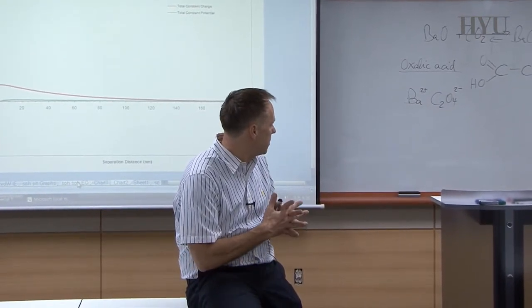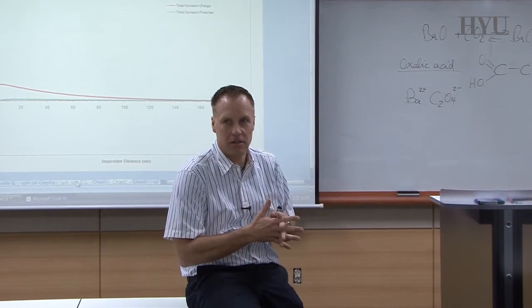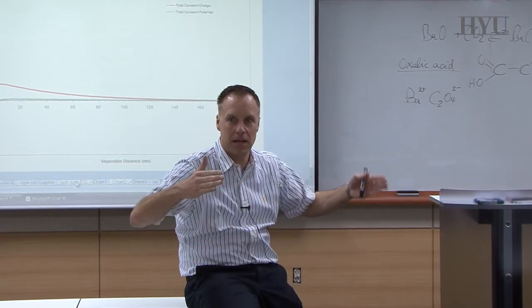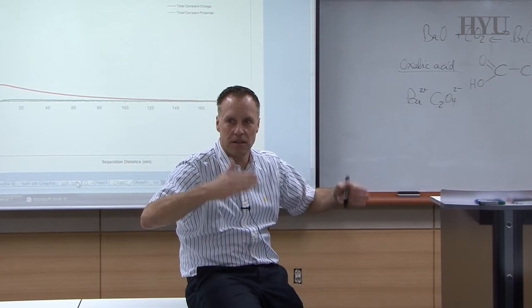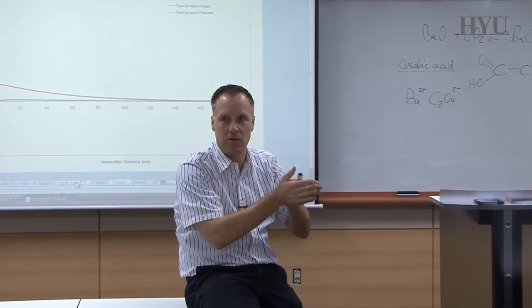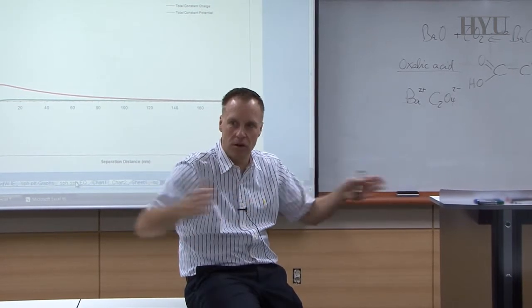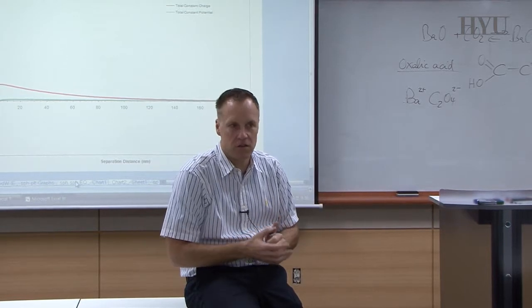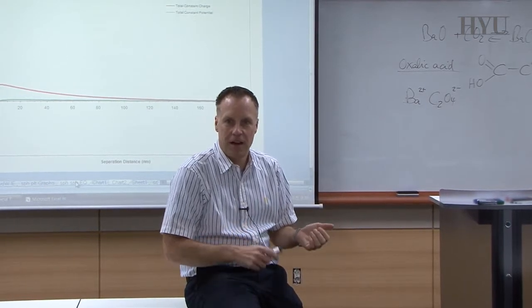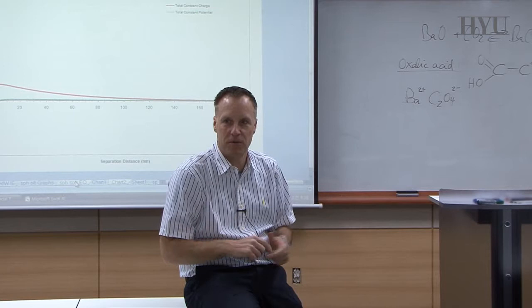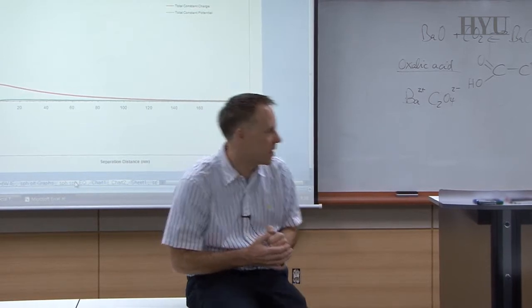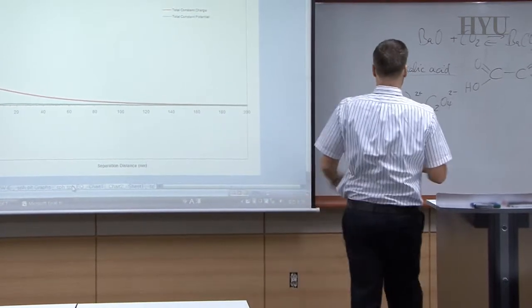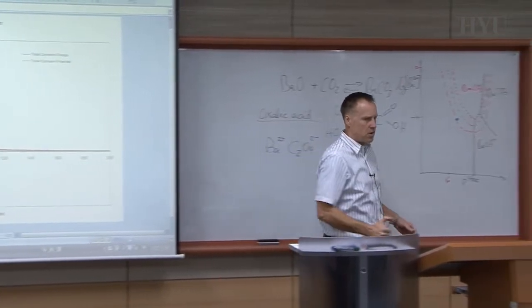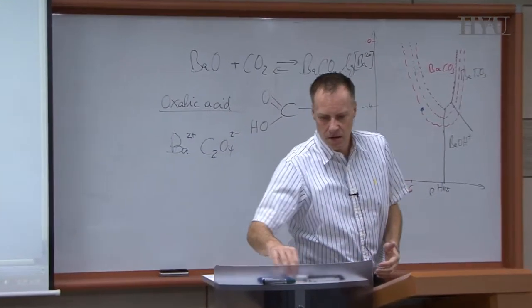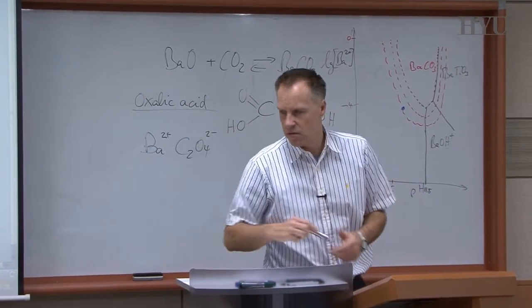And that is a much broader temperature range. So it's not as spontaneous and in a narrow temperature range. So you have an advantage that's a little broader. That's the main thing. So industry has an advantage. You have a little more leeway before things go really bad. Okay, so this barium oxalate is very insoluble, so you suppress the barium ion concentration down to 10 to